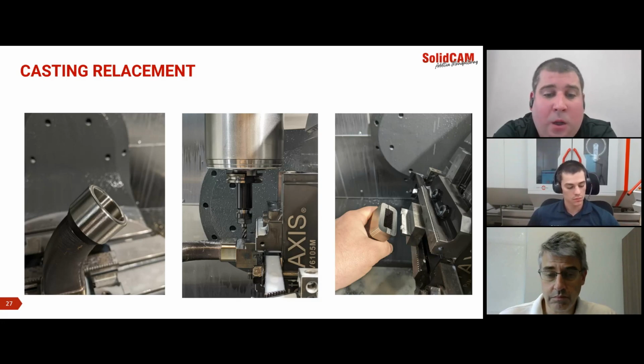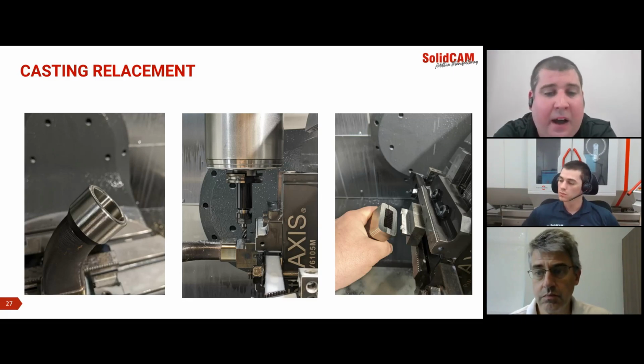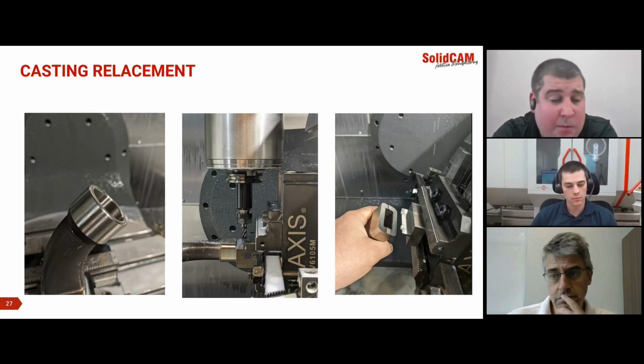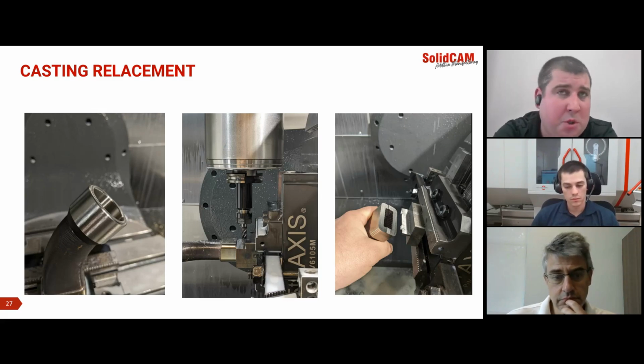So nickel-based super alloys, certainly a sweet spot for this type of technology because of how difficult it is to machine, as well as high cost for billets or castings of Inconel 718, 625, different Monel materials, Hastelloy materials. That's certainly a great application, or can be great applications for us. But a wide variety of stainless materials, titanium as well, titanium 6-4, is very common for us, as well as a pretty broad spectrum of steel, from tool steels like H11 and H13 to higher tensile strengths, like a ER100 or ER120 welding wire.